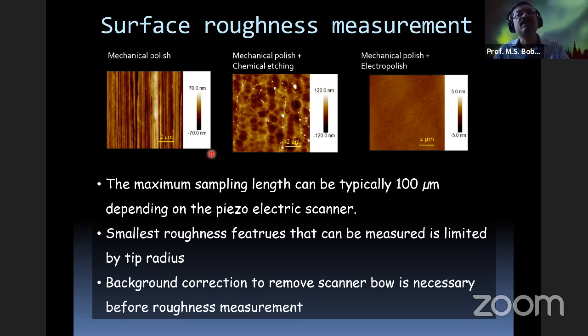When we do a chemical etching, taking this surface and putting it in a chemical like sodium hydroxide to etch out the roughness, you will see the roughness style changes and it becomes more rough, plus 120 to minus 120 nanometers. The roughness becomes a different kind. All the sharp peaks were removed and you get a very crater-like surface, like a moon surface. A lot of craters are on the surface, and also some peaks, because the material is not homogeneous. Wherever precipitates are there, they are not dissolved, so they form very sharp boulders, like a typical mountain range, like a Himalayan mountain ridge, which is not granite; you will have a lot of mud and some rocks sitting on top of it.